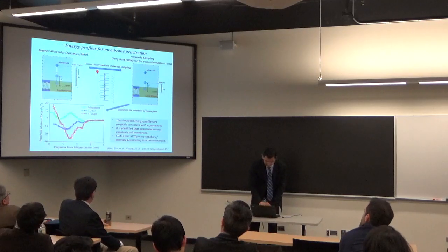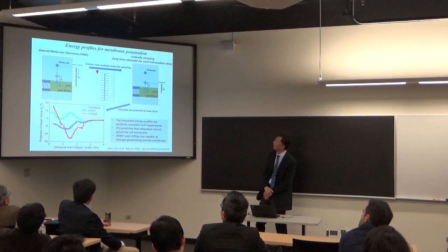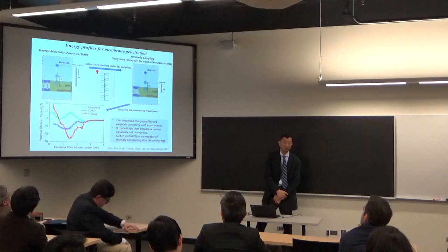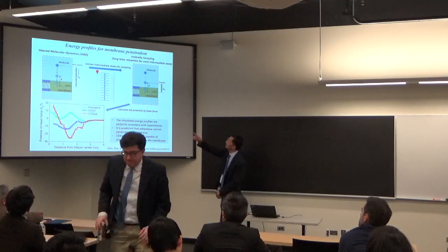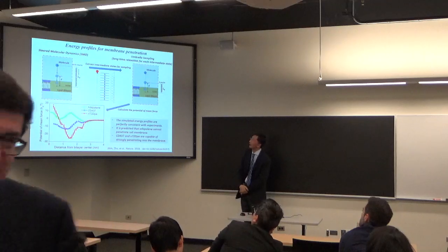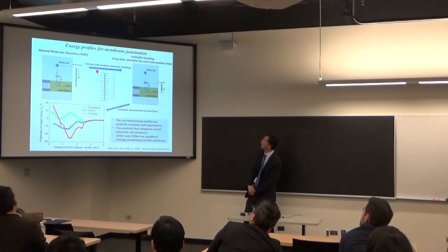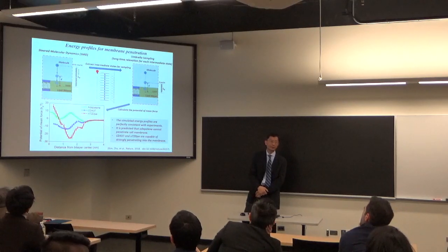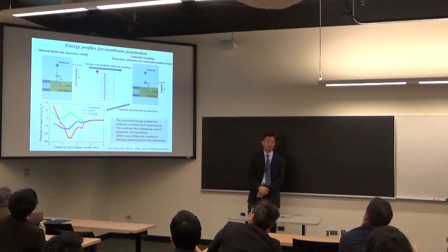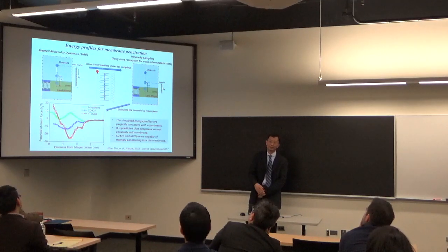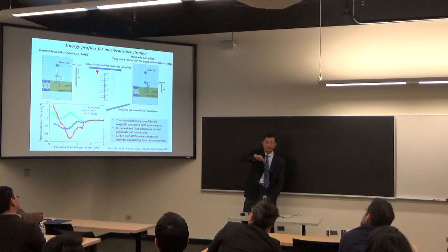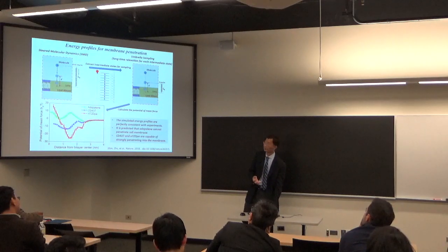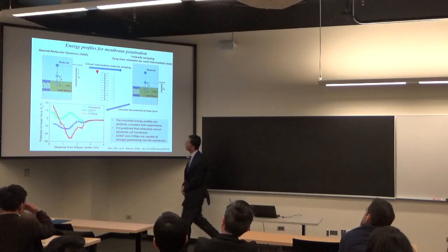So we developed a method to calculate the energy profile for the interaction of nanomaterials with the cell membrane. This is called steered molecular dynamics in the biophysical community. Specifically, the method called umbrella sampling. We can compute the free energy as a function of the distance between the nanomaterial and the cell membrane. So as you bring this nanomaterial to the cell membrane, how does the free energy change? The free energy consists of interaction energy and entropy, both parts. So we calculate these 3 molecules.